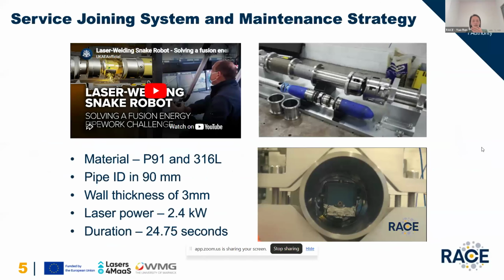Sorry. Yeah, I think I just introduced this system, which my colleague developed, and they carried out some feasibility study, which mainly focused on the thin material because of the power challenge. You know, compacting everything into a small tool which allows the tool to be inserted into a pipe with 90 millimeter diameter, the laser power was really limited to about 2.4 to 3 kilowatt, and we managed to weld through 3 millimeter wall thickness within about 25 seconds.